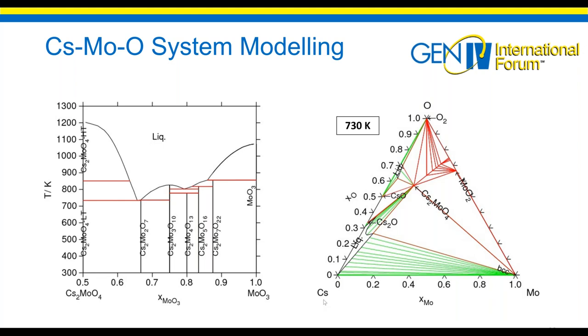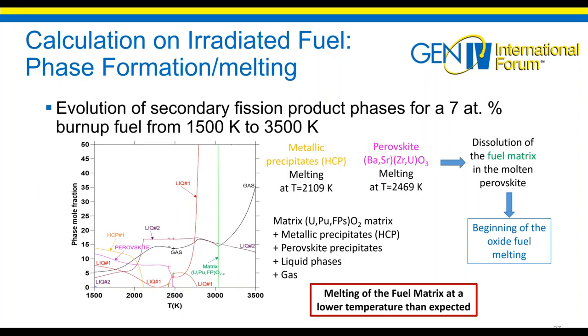And so this is a pseudobinary phase diagram, and you can have also a ternary phase diagram like here between cesium, molybdenum, oxygen. And there you can choose a temperature here and know which phases are stable at this temperature as a function of the composition of your system, which can be really useful. And also, you can perform calculations on irradiated fuel with, for example, following the evolution of secondary fission product phases between 1,500 K and 3,500 K.